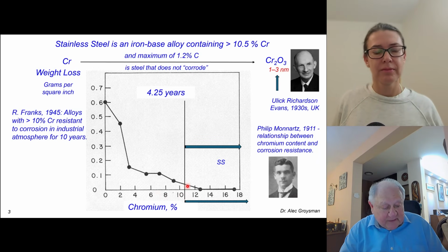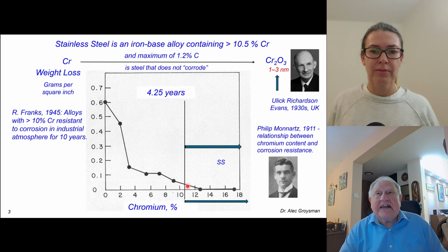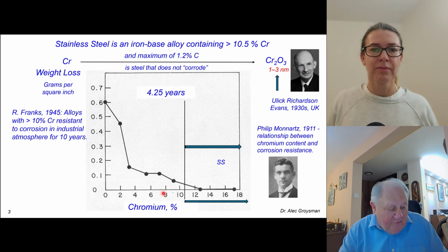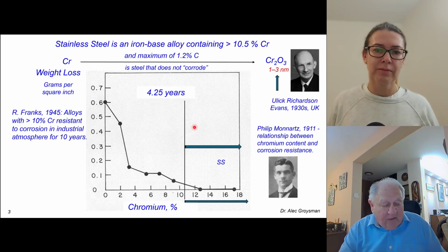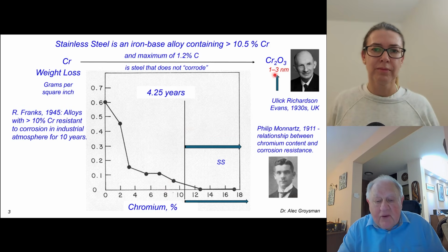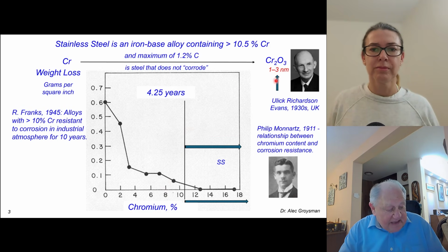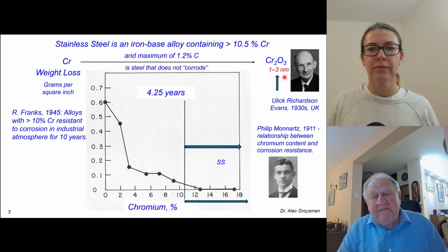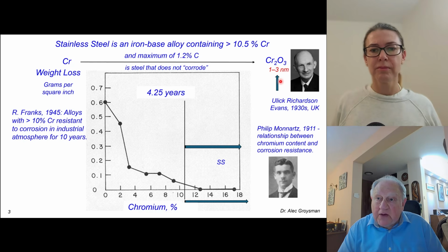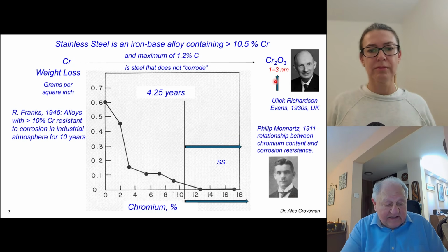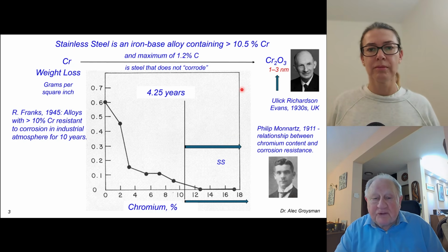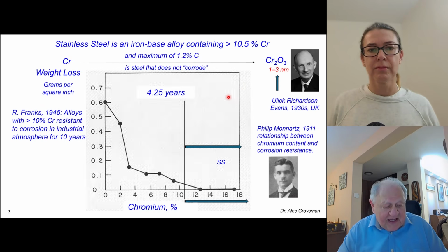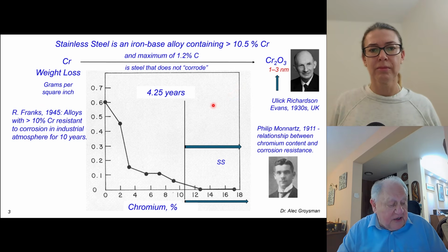The 10.5% chromium rule is a threshold, not an optimum. At about 10.5%, steel can form a continuous chromium-III oxide (Cr2O3) passive film in air. That film is thin, about 1-3 nanometers, and environment dependent. It can fail locally, causing pitting, crevice corrosion, and stress corrosion cracking. The chromium rule says nothing about how corrosion will occur.